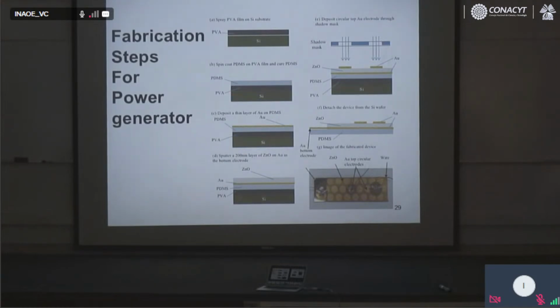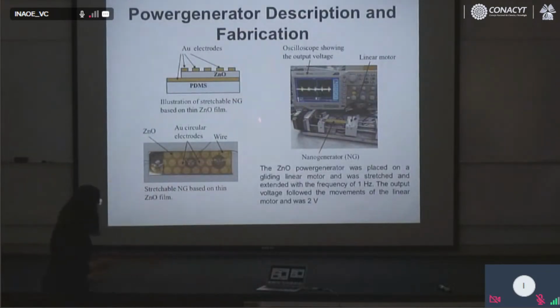And after you fabricate, you need to detach your sensor. And for this, you need PVA. PDMS is a polymer and it's very strongly attached to the silicon substrate, but this PVA lets the PDMS detach. And then we deposit gold. No, first you have PVA, then you have PDMS, and then you need to deposit the lower electrode. I think it's good to show you a little bit the image of the fabricated sensor.